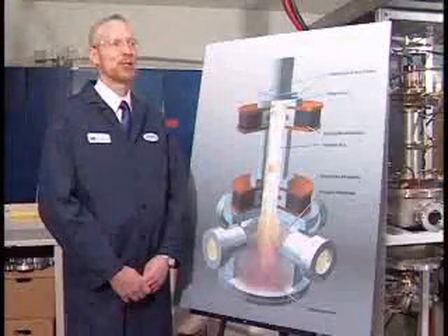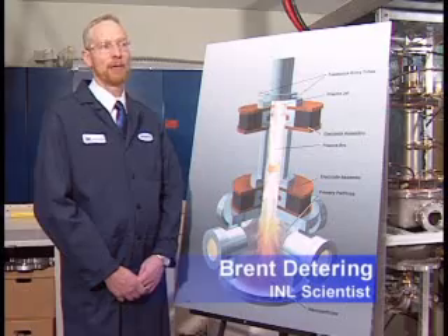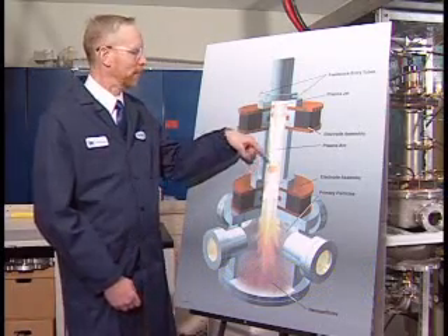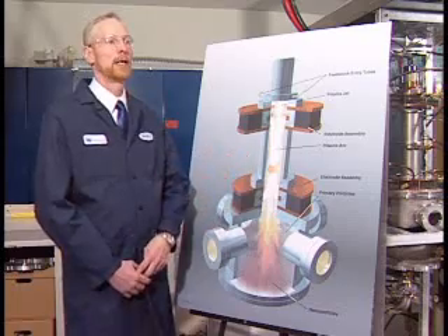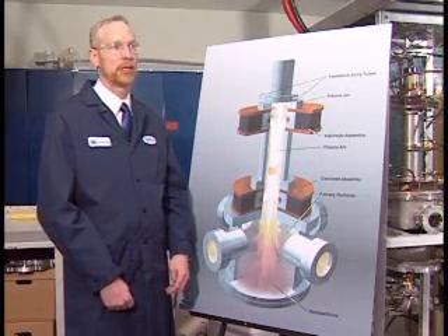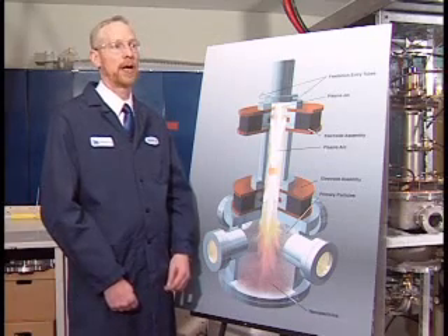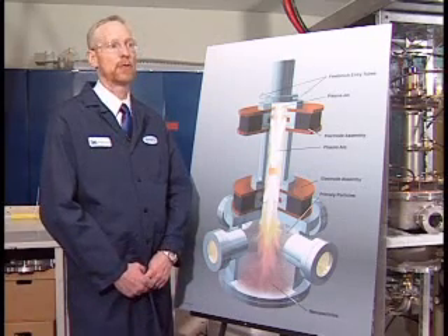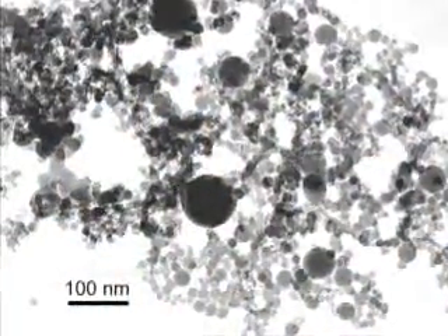To increase the stability of the fabrication process, we developed a self-induced magnetic field to rotate the arc within the plasma assemblies. The high-temperature sequential arc design vaporizes the materials, while the lengthy duration of the process ensures that larger materials at 200 microns are vaporized. As the vapor emerges from the last module, the vapor cools instantly, becoming supersaturated to form nanoparticles between 5 and 40 nanometers.